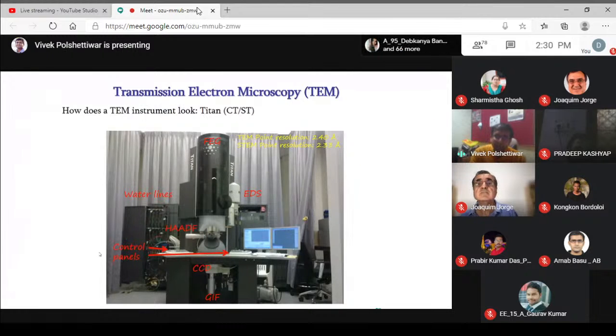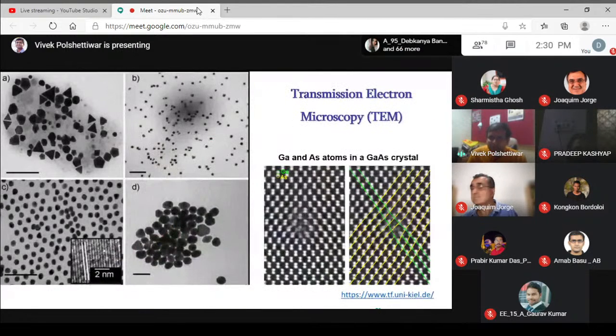This is how the TEM looks, and this is how transmission electron images look, right? So you get sizes, you get shapes, you can see whether they are monodisperse or crowded. You can get the distances. You can even get atomic resolution with HRTEM or STEM. You get highly resolved images, and you can even see the atoms and the distances between them, how they are organized. That way you can get the crystal structure of the material. You can also see defects. See, something is missing here, so you can also see the defects in the material. There are several other things that you can do by transmission electron microscopy.